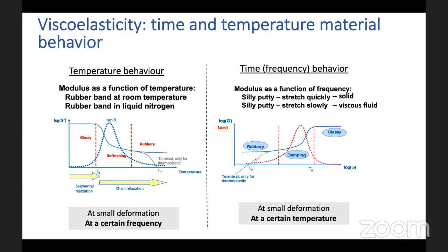Now viscoelasticity, time and temperature. I will talk about the time and temperature behavior now. I will again repeat a bit, to reinforce this concept. So temperature behavior: if you plot the shear modulus, shear storage modulus, or tensile storage modulus as a function of temperature, you will see the modulus start decreasing, and from the glassy state to the rubbery state you will have a change in modulus at the glass transition. The maximum of tan delta here is what we call the glass transition temperature. So this is the mid region of this transition.